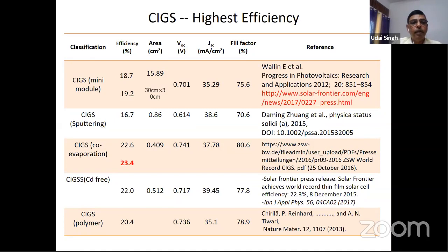Copper indium gallium selenide, there are different ways to manufacture this copper indium gallium diselenide. If you do it by sputtering, the highest achieved is 16.7. If you go by the co-evaporation method, recently it has been updated to 23.4, which is the highest.